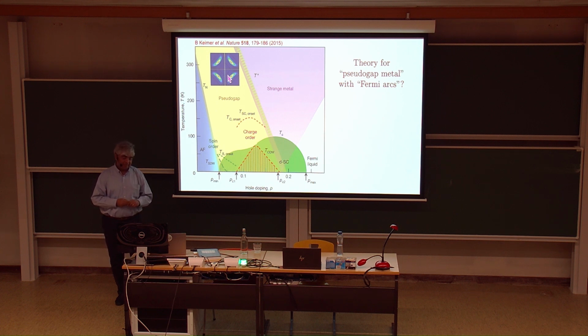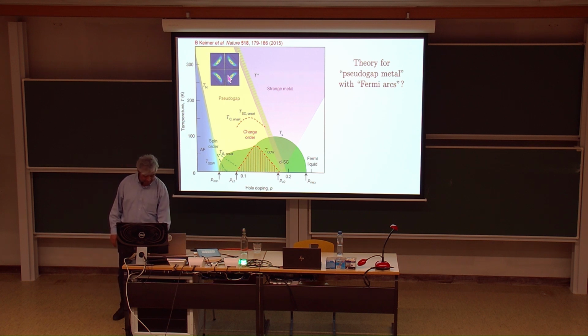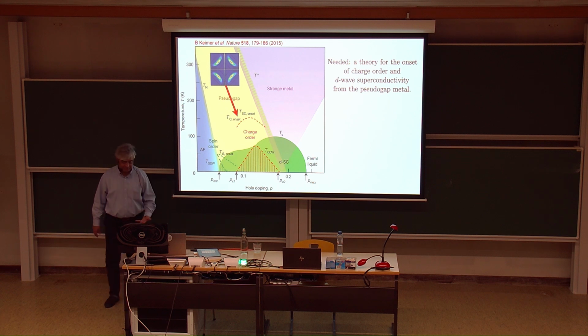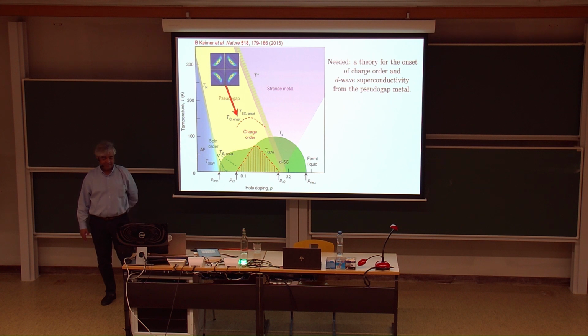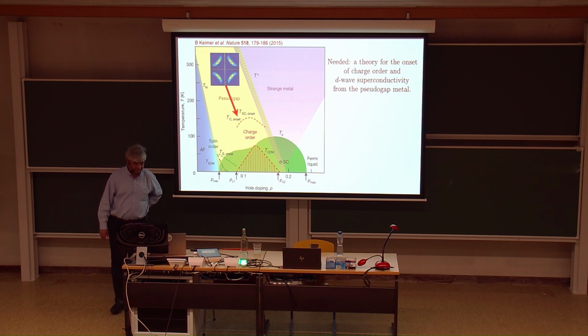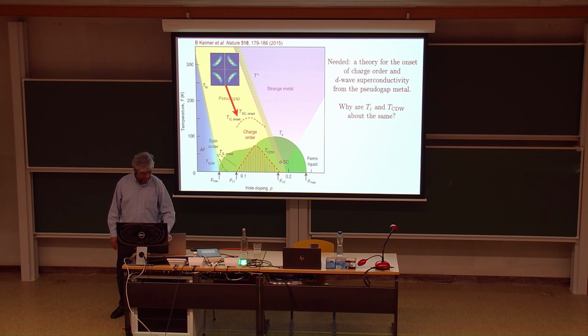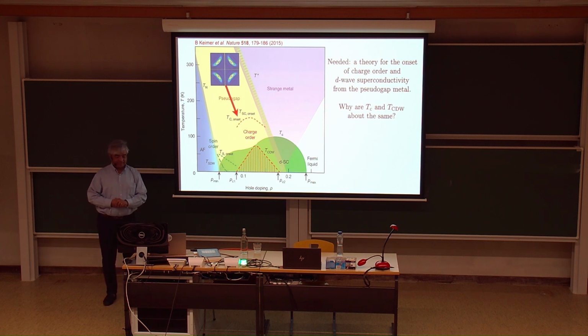All right, so first of all, to begin anywhere, before we even talk about superconductivity, I think many of us have believed that you need a theory of the pseudogap. You need to understand what the state is. And then, once you understand it, just like we did for the Fermi liquid, we ask what are the low temperature instabilities. So we need a theory for the onset of charge order and D wave superconductivity from the pseudogap metal. And one of the things you noticed has also been kind of emphasized in this plot by Hamidian et al. is that the instability temperatures of Tc for superconductivity and for the charge density wave are about the same.